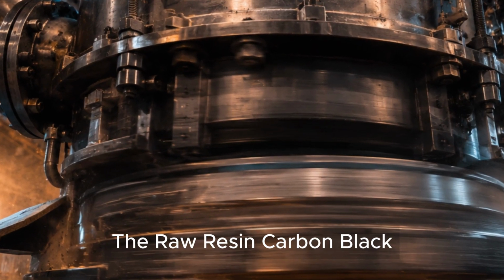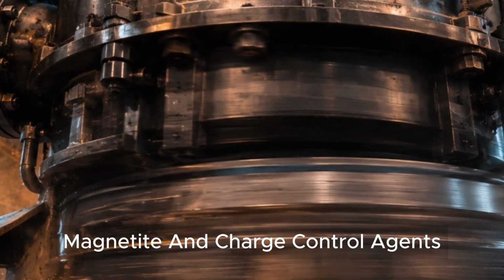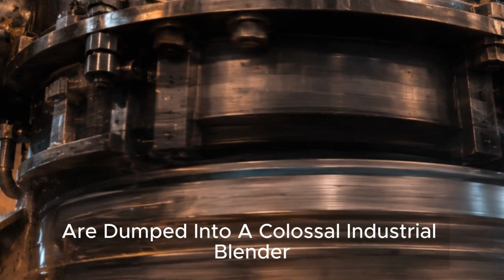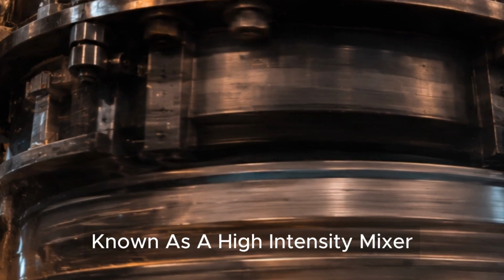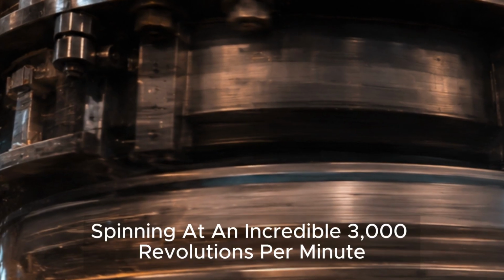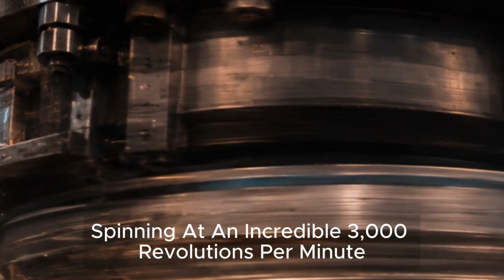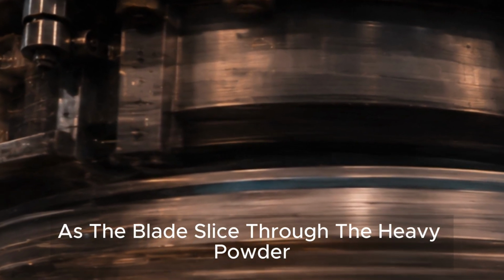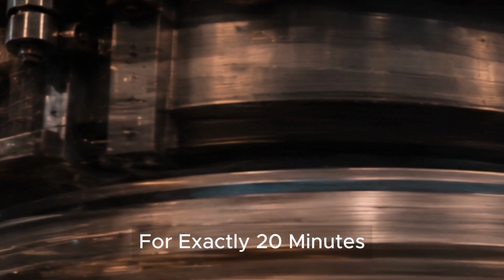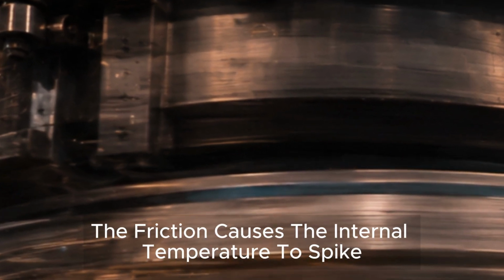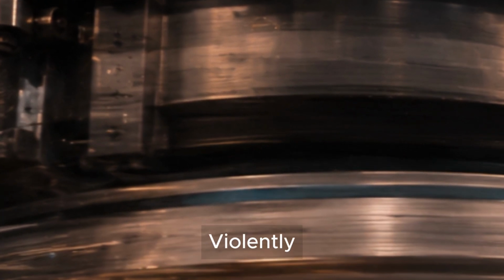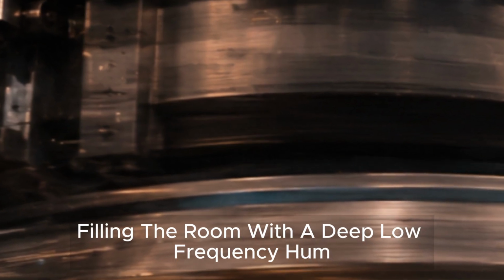The raw resin, carbon black, magnetite, and charge control agents are dumped into a colossal industrial blender known as a high-intensity mixer, spinning at an incredible 3,000 revolutions per minute. As the blades slice through the heavy powder for exactly 20 minutes, the friction causes the internal temperature to spike violently, filling the room with a deep, low-frequency hum.